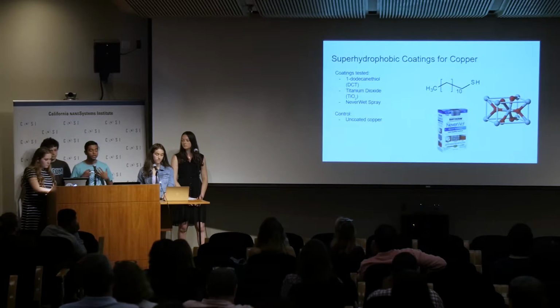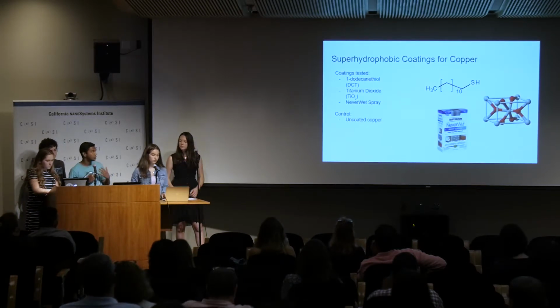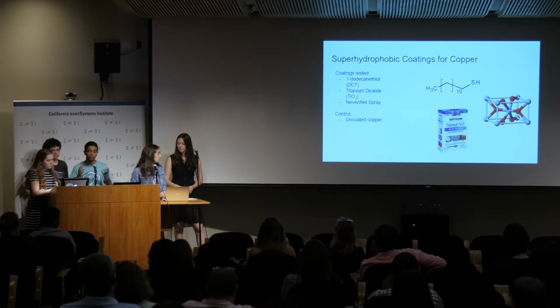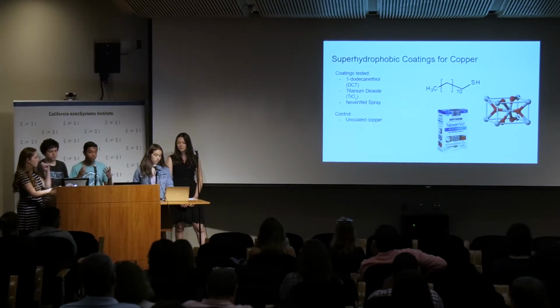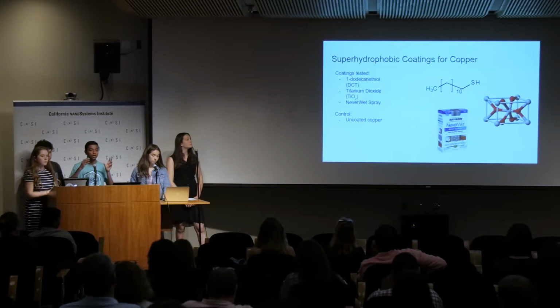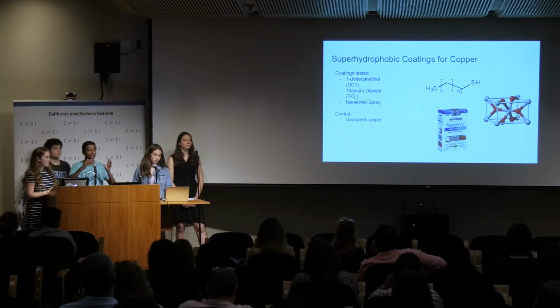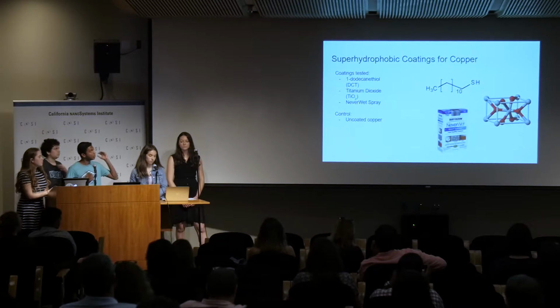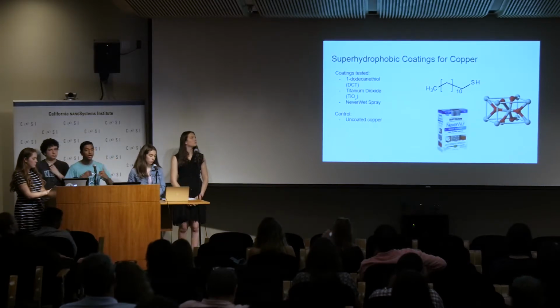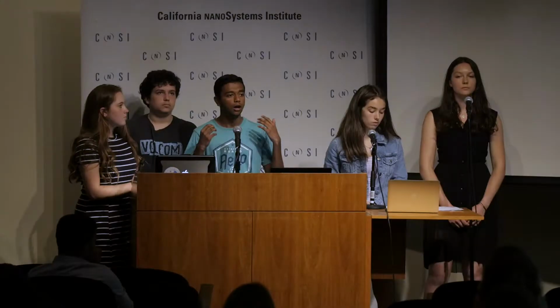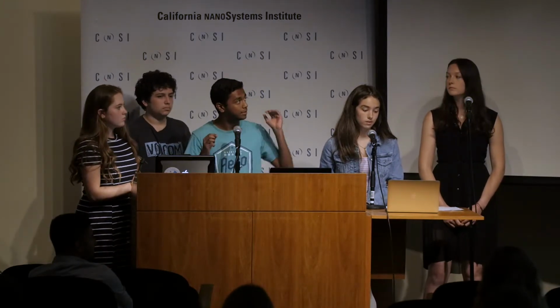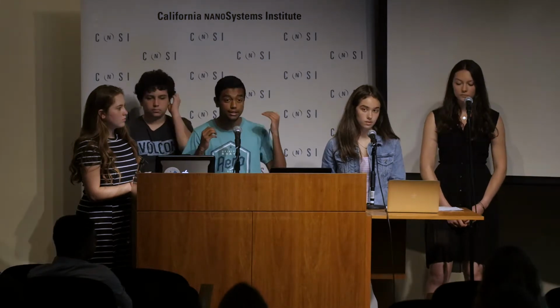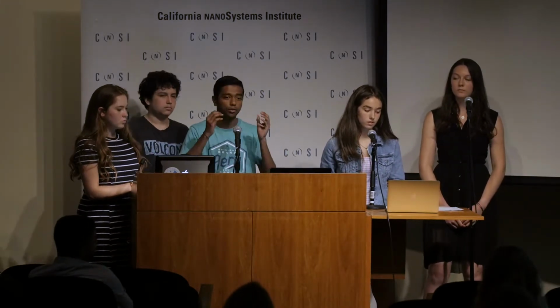In our experiment, we used 3 different coatings, and each of these hinges upon the fact that we use nanoparticles to induce superhydrophobicity, which basically stops any kind of water or acid or anything else from touching the metal on the inside. Our first coating was a DCT coating. In order to do this, we first took our copper slides, sanded them down in order to remove the oxide layer, then submerged them in silver nitrate in order to create silver nanostructures, and then submerged them in DCT in order for the DCT nanoparticles to bind and, with their nonpolar tails, create the superhydrophobic layer.